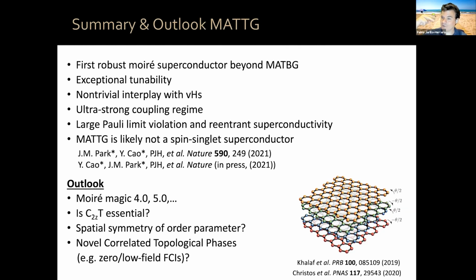Because there you still have 2 degrees of freedom left, and you can valley polarize, spin polarize, or polarize in a more global SU(4) state. Okay, you can be spin valley polarized, or in a linear superposition of all of these things. So that is more complicated. From our initial transport experiments, when we applied a magnetic field out of plane or in plane to the nu equals 2 correlated insulator state, the resistance decreased. That led many people, including ourselves, to believe that the nu equals 2 correlated insulator state was spin unpolarized, okay?